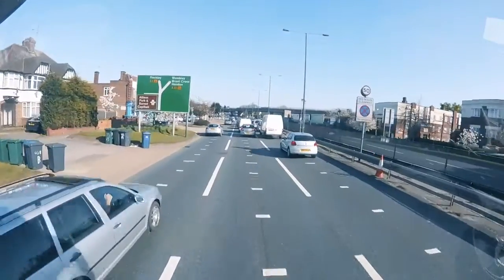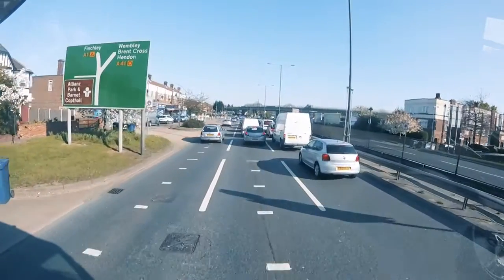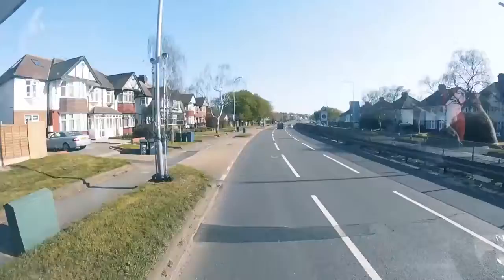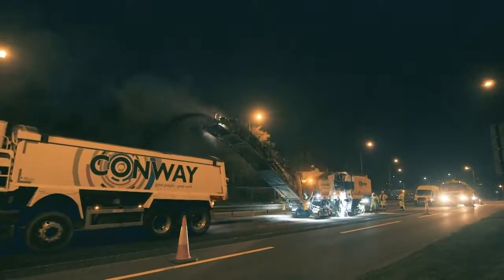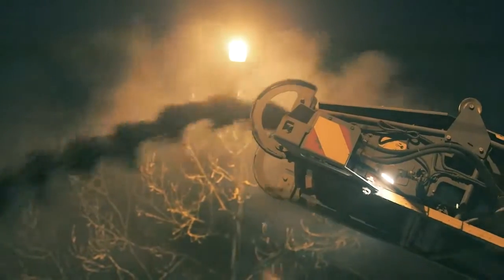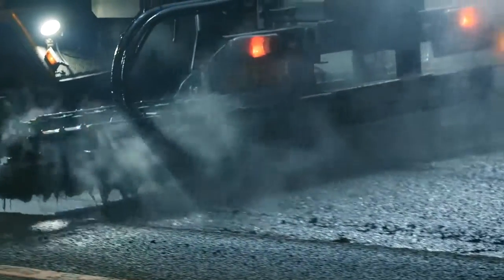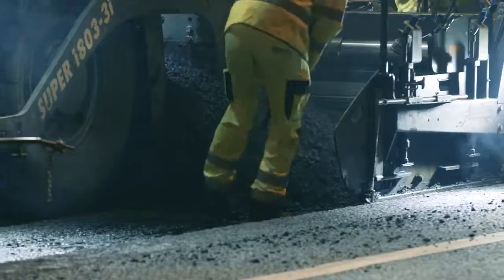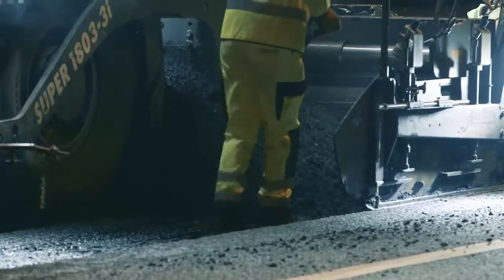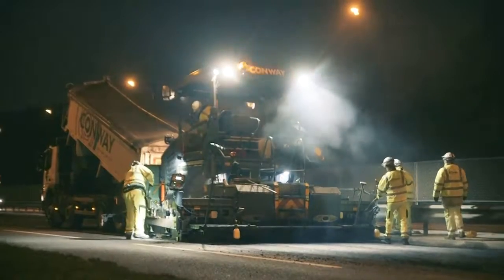The actual area decided on in the end was the A1 at Mill Hill — a three-lane section of an existing SMA type surface course. We set out to replicate what's there in terms of material look and assess its durability over the long term, putting it like-for-like against material with no recycling at all. Assessment will take place over the next six months, twelve months, and twenty-four months.